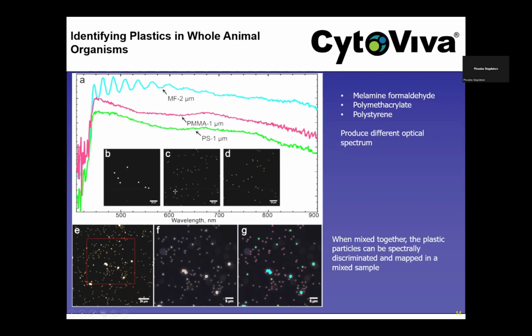And you see these different polymer materials just isolated in solution. And then you see them here as well. And in this third example that we show here, these 3 different polymers have been mixed. And then he spectrally mapped each one of the 3 different polymers in different concentrations here. And so one of the polymers is mapped in red, another is mapped in green, and another is mapped in cyan, to demonstrate the ability to identify these polymers when they're mixed together in an environment, to distinguish one from the other and know what you had.